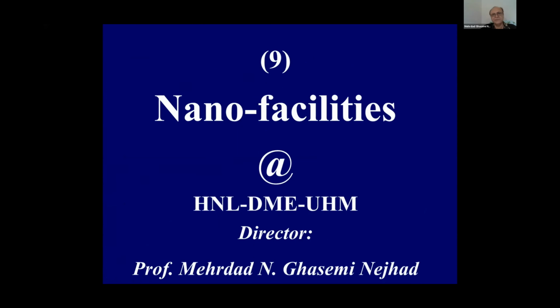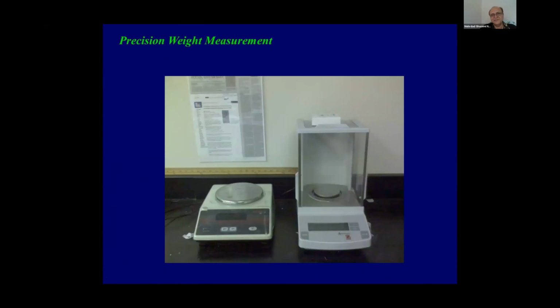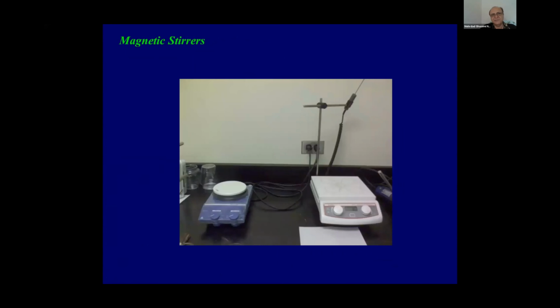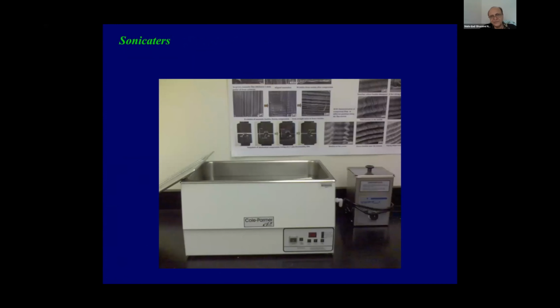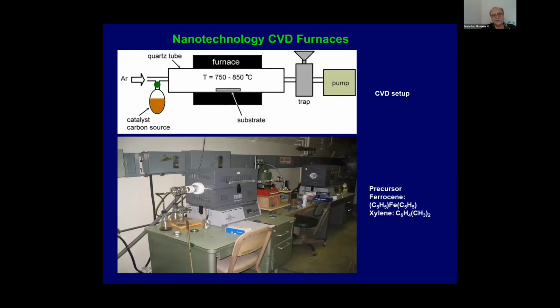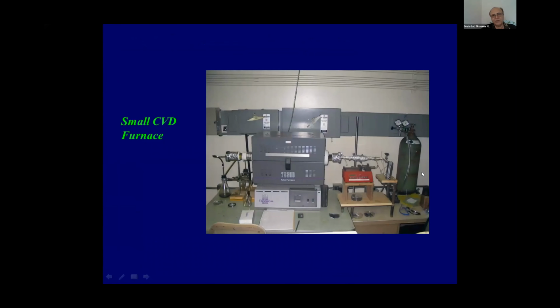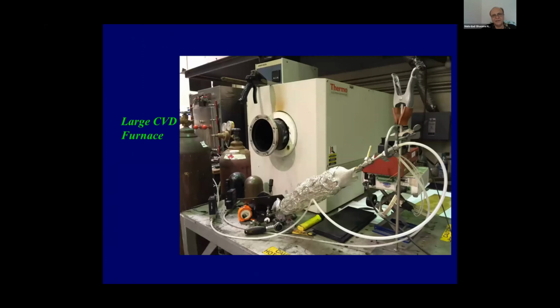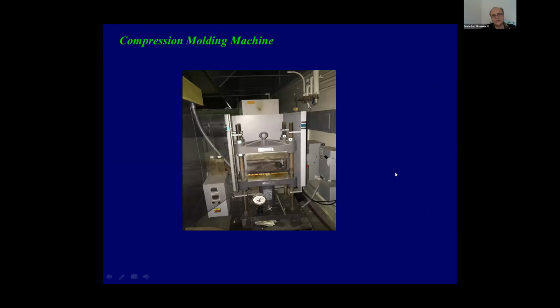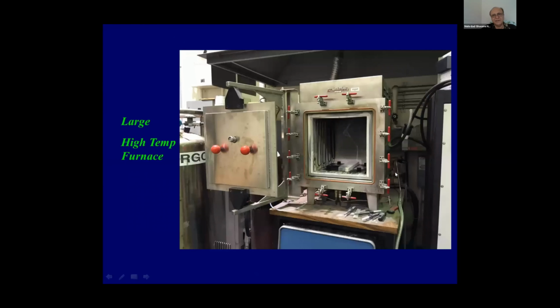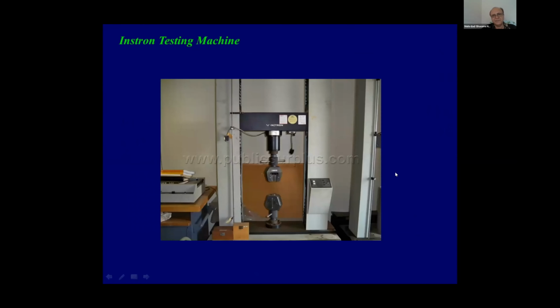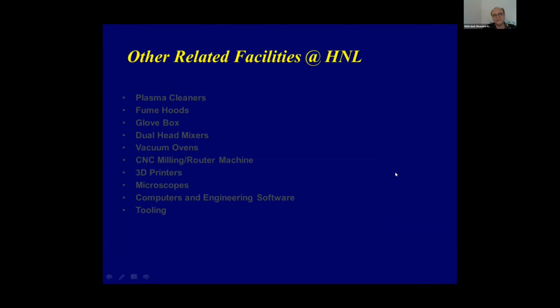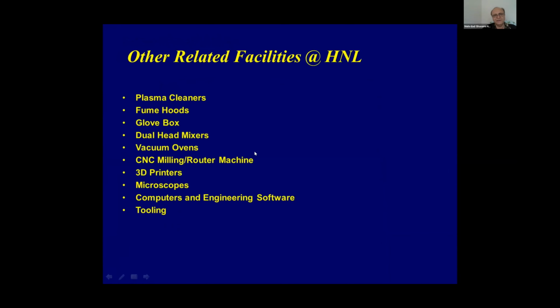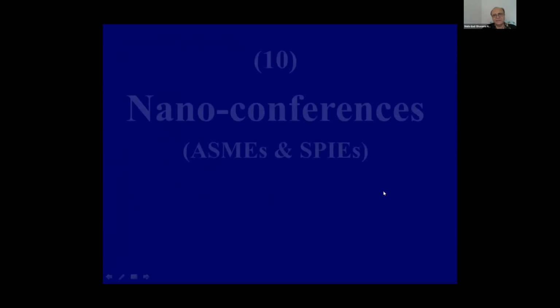I'm running out of time. I'll just quickly flash the facilities we have. This is a precision weight measurement, magnetic stirrer, sonicator for dispersion of nanomaterials, spin coater, chemical vapor deposition furnaces. This is a small one we have. This is a larger one we fabricated in-house. This is a hot press. This is an autoclave. This is a high temperature furnace for ceramic processing, and then we do testing with the Instron machine. And we have others, like a glove box and dual mixer, etc.